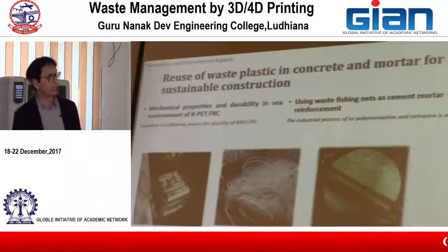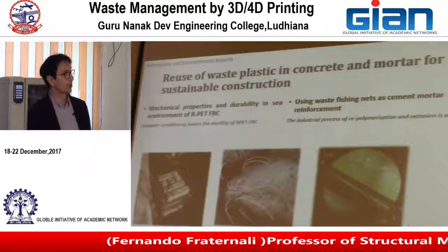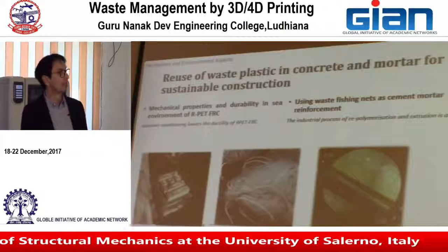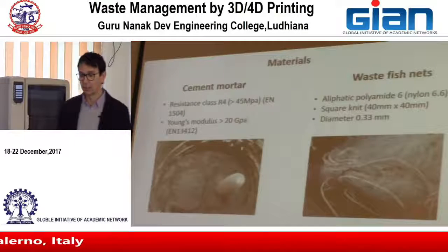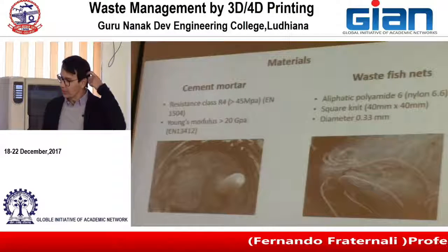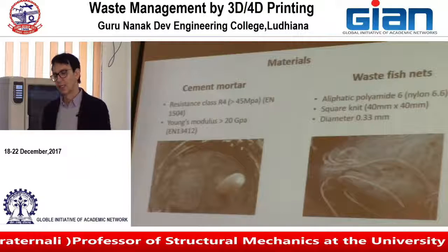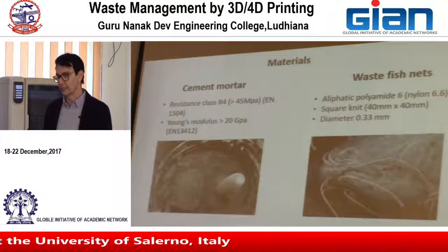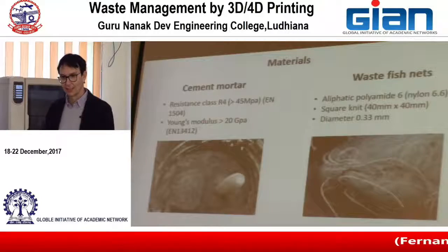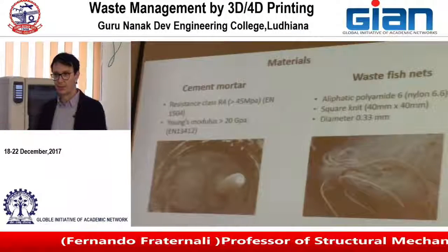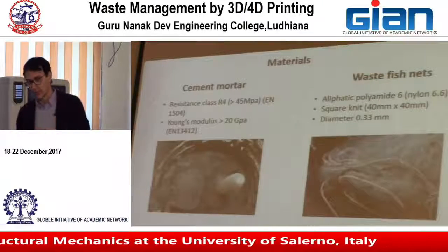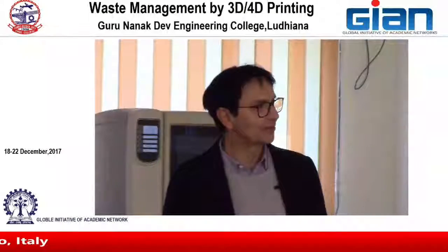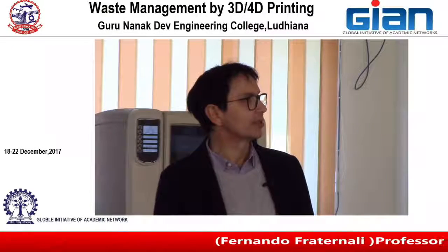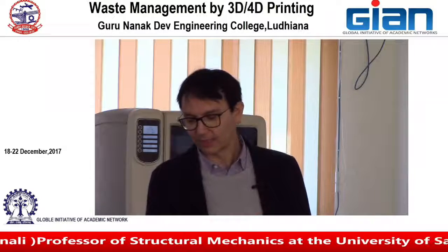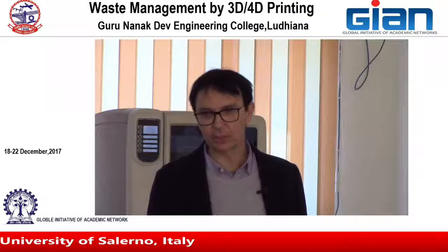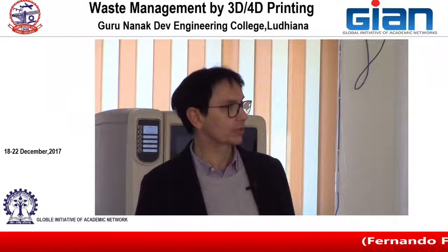In this particular study, I want to describe the cement mortar reinforcement using waste fishing nets. So in Salerno, close to our university, there is a company that recovers fishing nets that are abandoned in the oceans. They are basically stored by the police in some hangars. This company was using some of this material for recycling purposes, and we obtained some waste fishing nets that we characterized, and we mixed it to a cement mortar. And this was, as in the case of the 3D printed fiber, a commercial mortar, not a laboratory made. It was the same commercial mortar that I have shown before.